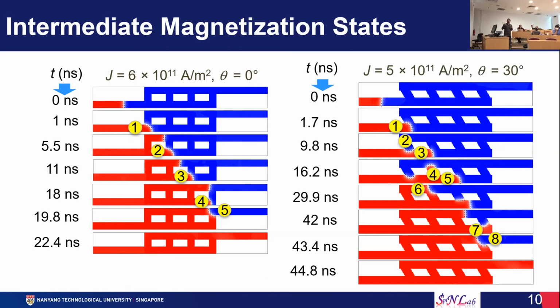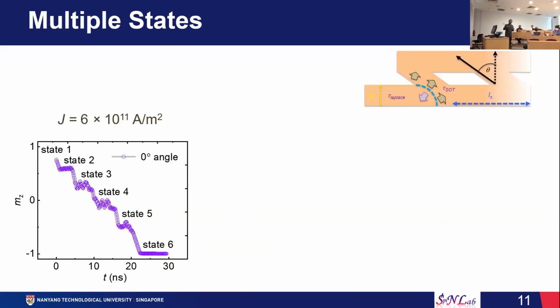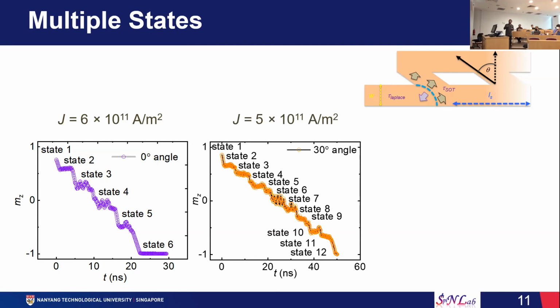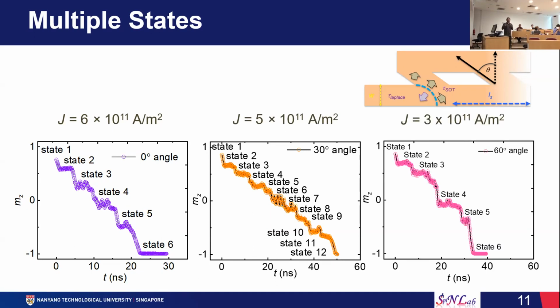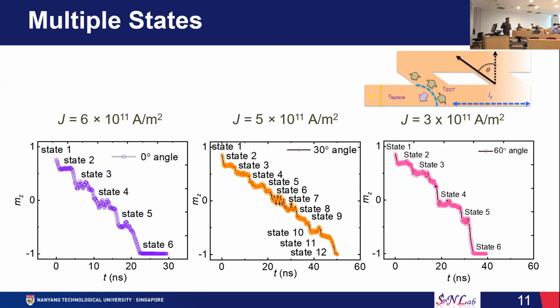Now the same simulation is observed for 30°, but we see differences. The number of pinning sites increases, because this angle provides that. Taking this information and plotting it as a function of time, we see this staircase nature. There are multiple resistance states, multiple magnetization states, which in the electrical signal are multiple resistance states. For theta equal to 0°, these 6 states are observed, for 30° this number of states increases, and for 60° it decreases again. This is due to the larger Laplace force observed for the 30° case. That's why the number of states is maximum for this particular case.